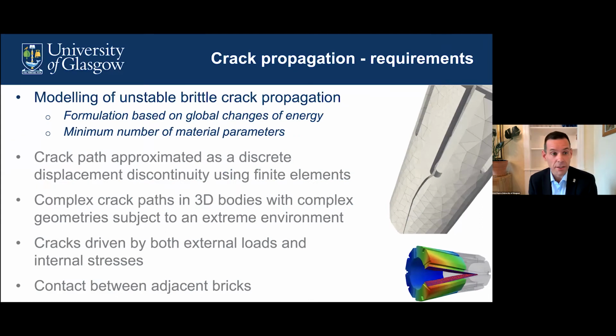So that's the context. We have been working on developing a modeling framework for modeling the unstable brittle crack propagation in these graphite bricks. It is a formulation that's based on global changes of energy with the minimum number of material parameters. In fact, the only material parameters we use for quasi-static analysis are Young's modulus, Poisson's ratio, and fracture energy.